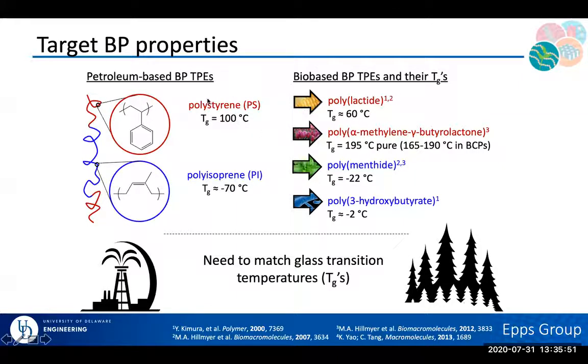So if we look again at polystyrene, we're also doing a lot of work with low glass transition materials such as polyisoprene. I'm not going to focus on that in this particular talk, but there is definitely ongoing work in that area. What I will focus on is, for example, polylactide, one of the more famous synthetic versions of bio-based polymers. In this particular case, it has demonstrated some very nice commercial potential. However, one of the concerns, if I'm going to use that, for example, with my hot coffee or hot tea, is that glass transition temperature of about 60 degrees Celsius is really going to prevent use in those applications.